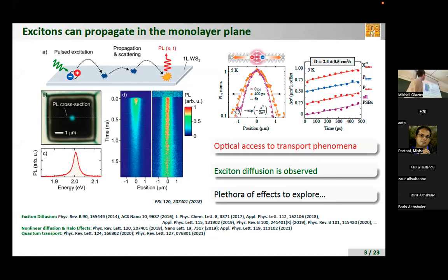Thank you for this point. Well, you can see here in this panel, I hope that you can see the pointer. The points are experimental data, and then there are the Gaussian fits, which is more or less what I expected for diffusion. Unfortunately, the studies of the tail, as far as I understand, are beyond experimental accuracy. I will try to prove that, at least in high quality samples, this is a kind of diffusion related to free propagation of excitons and scattering by phonons. So it is not hopping between localized states. But there are some other samples, I'm not going to talk about them right now. Indeed, there excitons are localized, and in this case one can observe even something like sublinear expansion of this width, which can be a signature of some returns and things like that. I'm not sure whether I have answered your question. No, completely. Thank you.